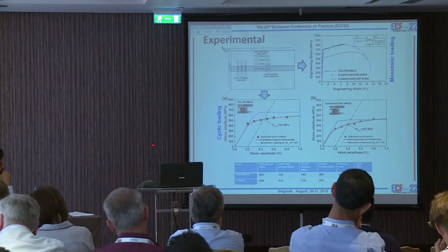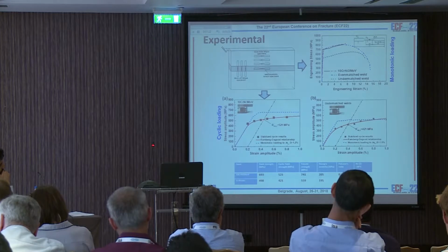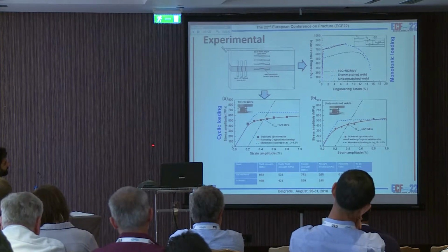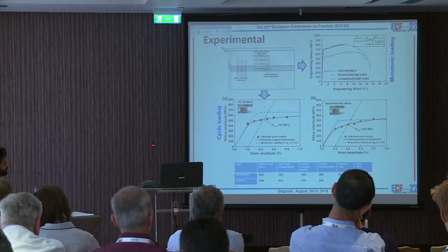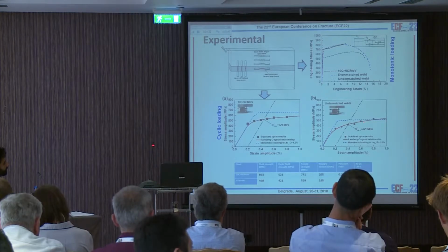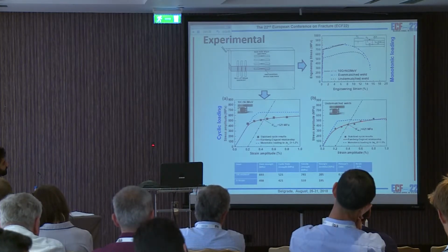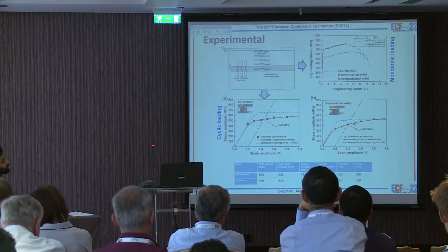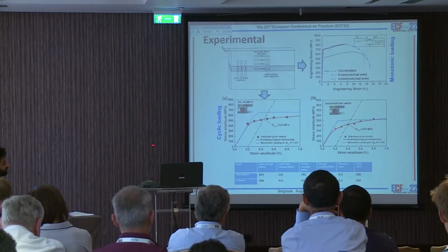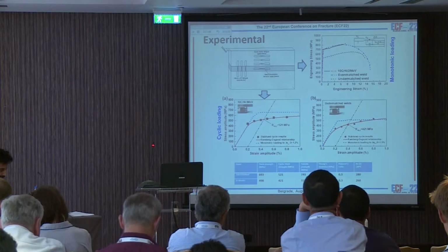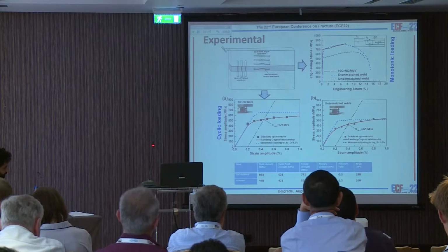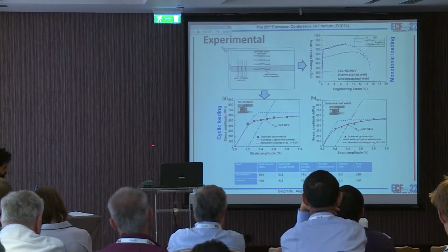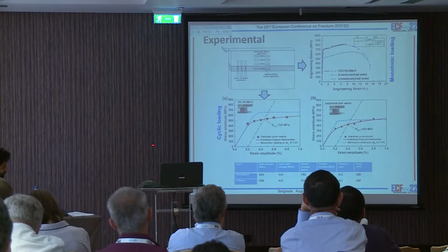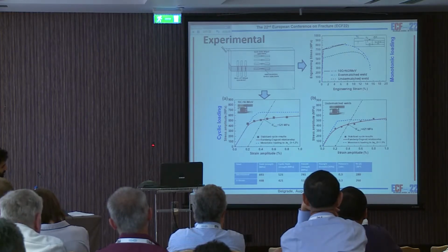This is the monotonic loading, and this is the cyclic loading. So some softening phenomenon occurs in these materials. And this is the undermatched welded joint. We can also see some softening effect of this material, and finally we give the mismatch ratio between the materials of about 0.7 to 0.8.